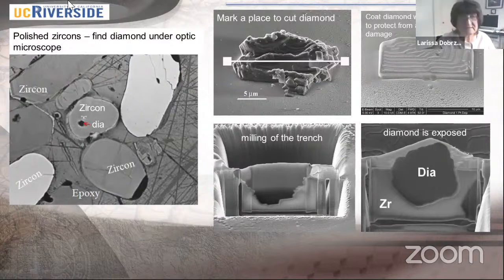So you see the details of the diamond. This is again polished zircons. Again, you see diamond. You found the diamond of your interest, so you polish it very well. This is how the diamond looks. You made the mark. You want to cut this diamond along this direction. Then you have to coat this diamond with nickel, because the ion beam is a very strong energy beam. It can damage diamond, destroy molecules of carbon. To protect from this damage, you coat with nickel. So then the milling started. And you see here, this is the big trench, another trench you don't see from here, but this is our foil.